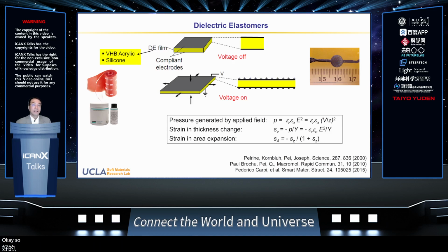Okay, so with the electrostatic pressure at the applied field of 100 volts per micron, that pressure is on the order of about 1 megapascal. That's a very high pressure. With human muscle, we can generate a pressure usually less than 100 kilopascal. So the Maxwell pressure here is something that's 10 times higher than natural muscle.